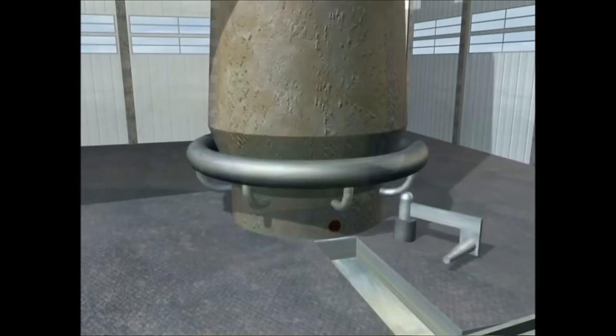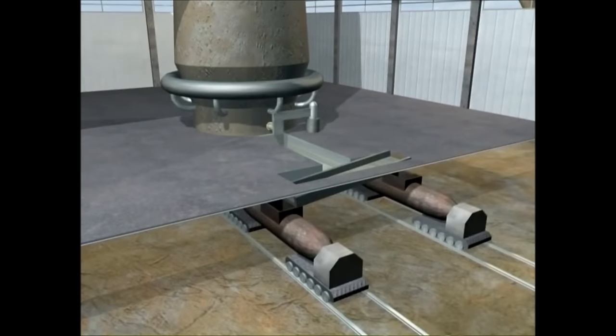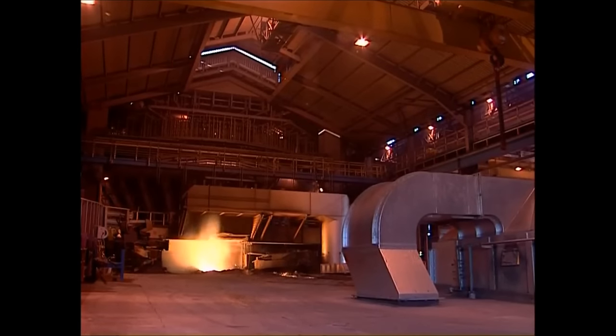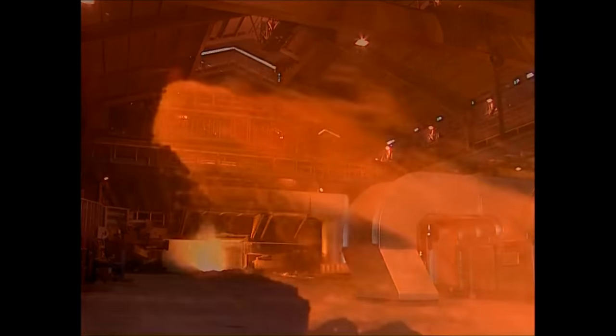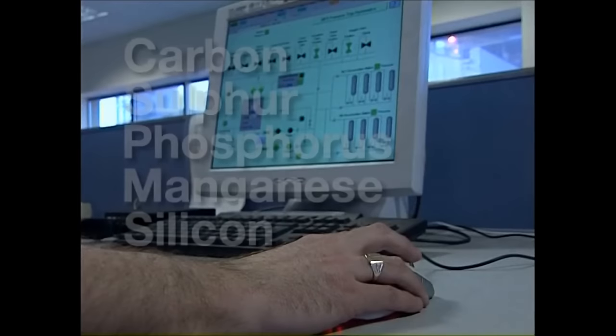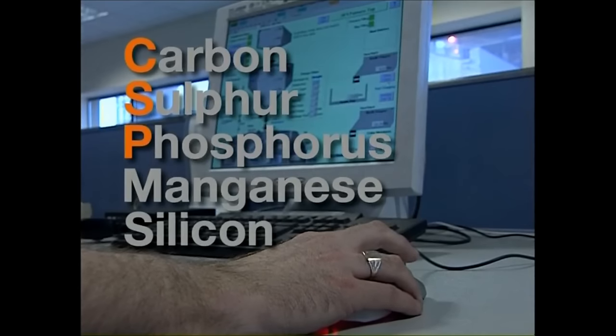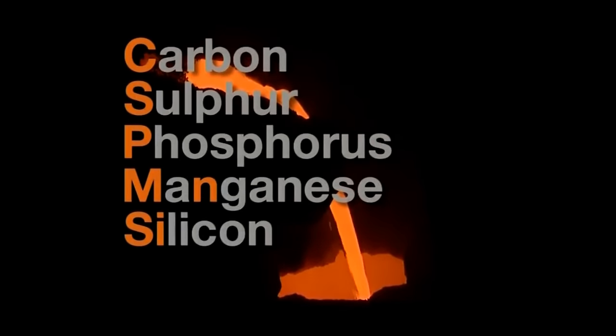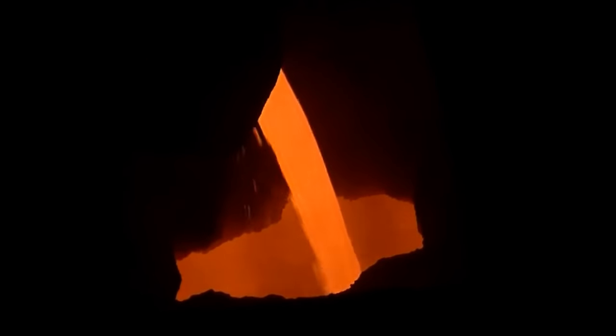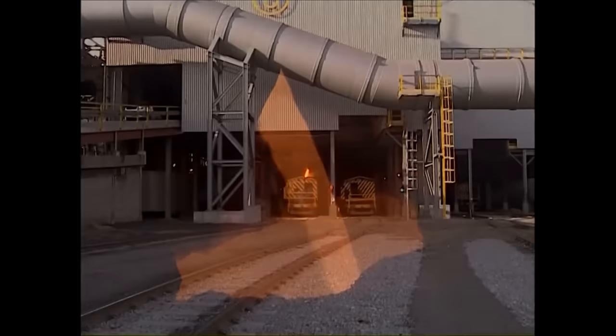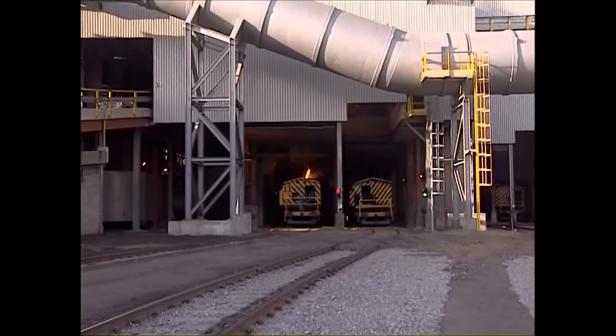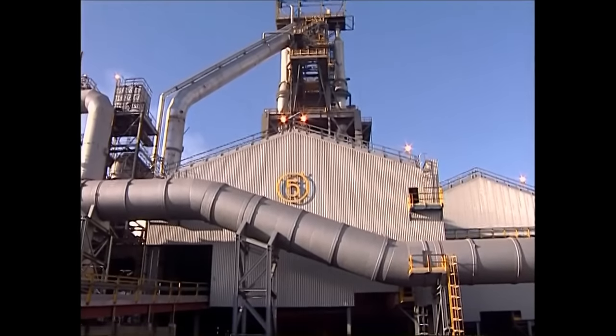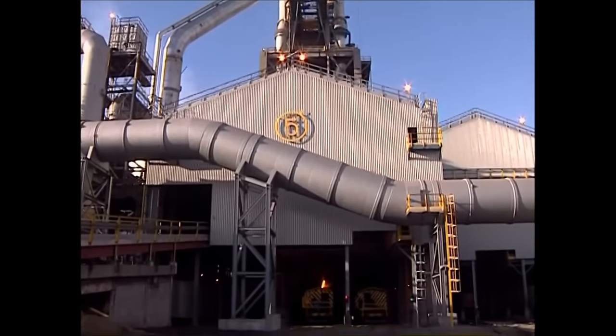The molten iron is tapped from the furnace and the slag skimmed off and taken away for use in other industries, such as road building or cement manufacture. The molten iron we get from a blast furnace, or hot metal as it's known in the industry, isn't pure iron and contains the elements carbon, sulphur, phosphorus, manganese and silicon. To make steel, these elements must be removed or reduced and other elements added, depending on the type of steel being made. The carbon content, at about 4%, makes iron very brittle and unsuitable for rolling or forging. And although iron can be used for castings, most of the iron produced is for processing into steel.